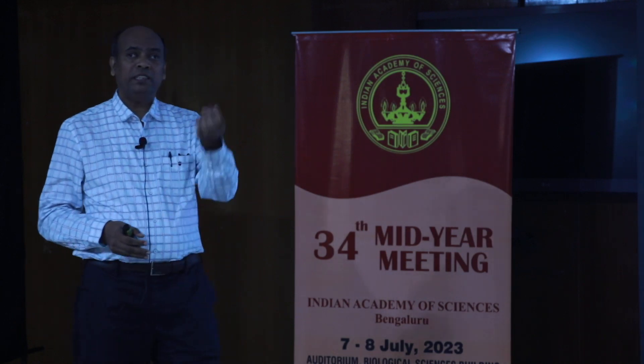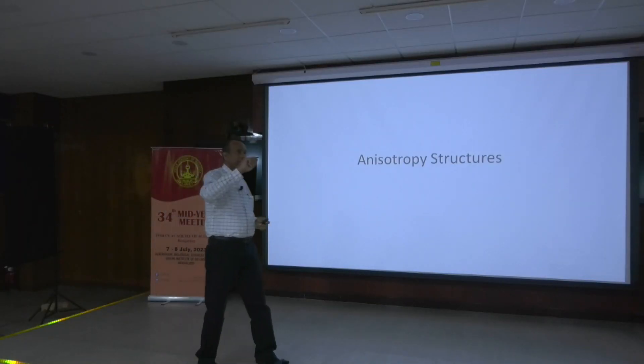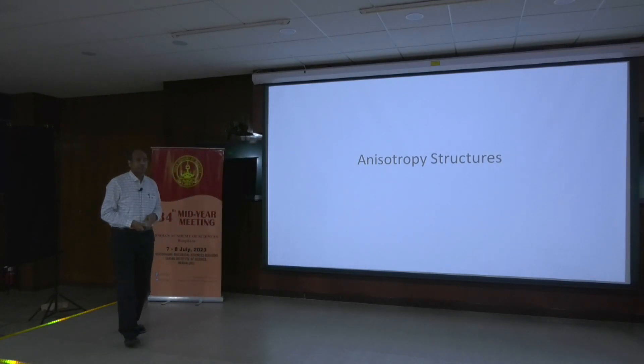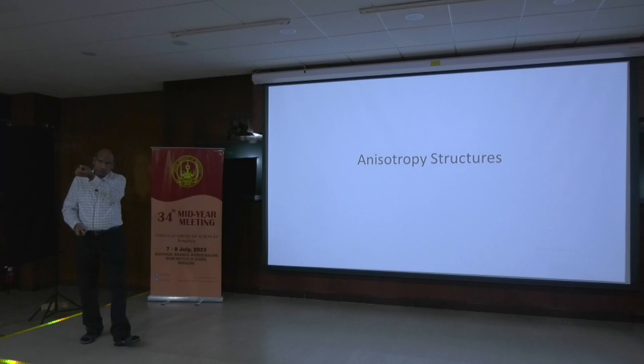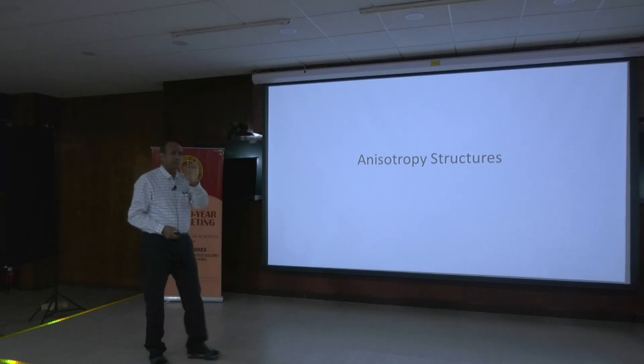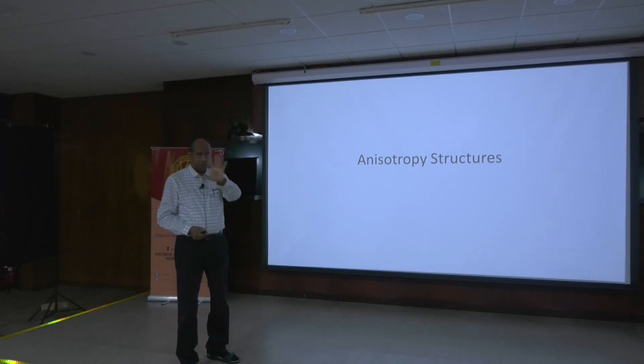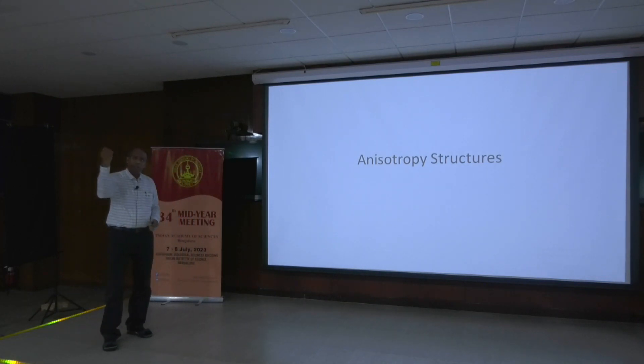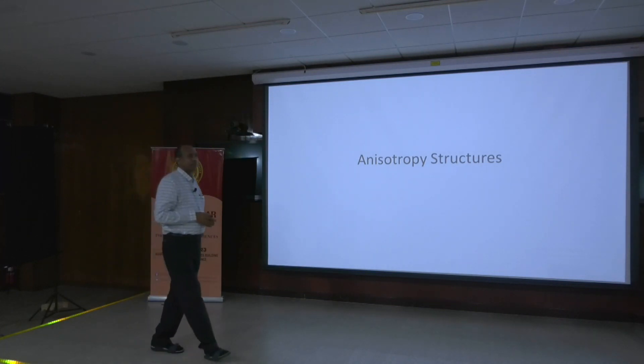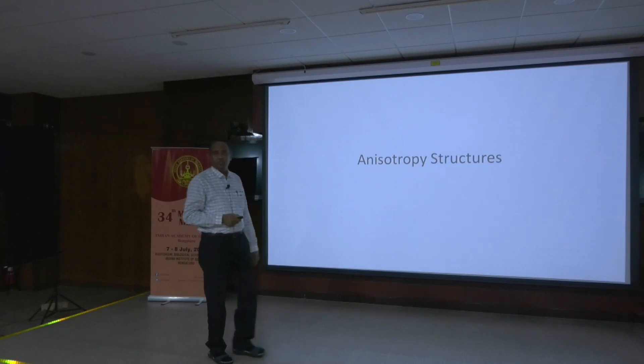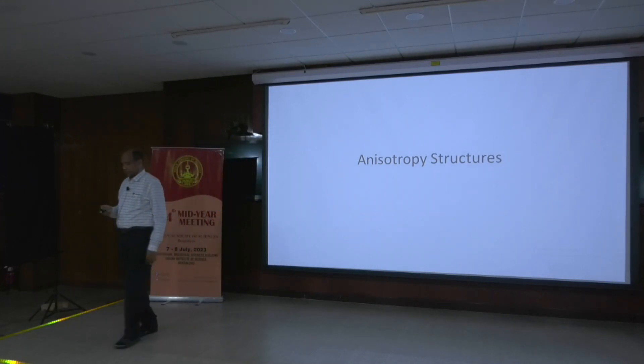Once given a cube or anything, you cannot make a rod, no way. There is no way you can make a rod. But if you see anything, you put zinc oxide structure, you get rods. So many thousands of papers on zinc oxide, zinc sulfide - you get rods. But any ionic crystals, sodium chloride to start with - nucleation starts as a rod? No, you can't get it. Because everything you inject finishes the reaction in one second. You don't have reaction time to change over from nucleation to growth. That is the problem of these structures.